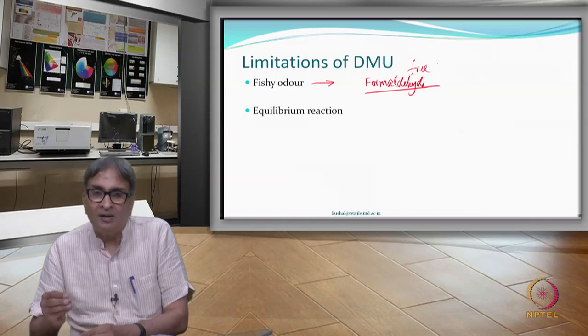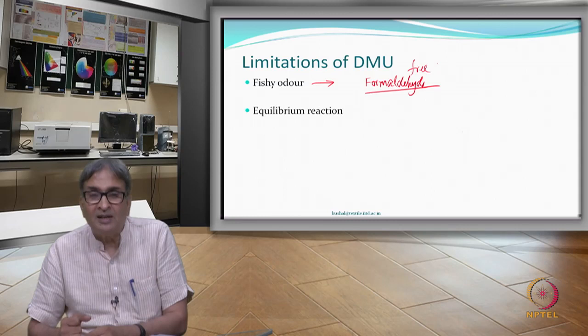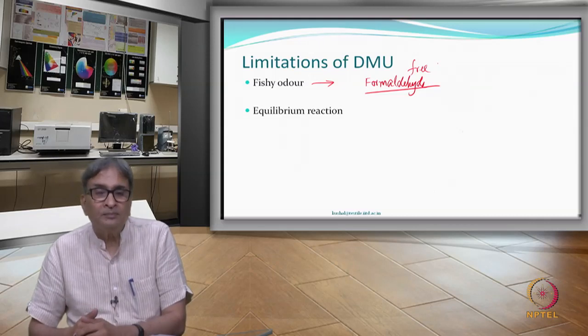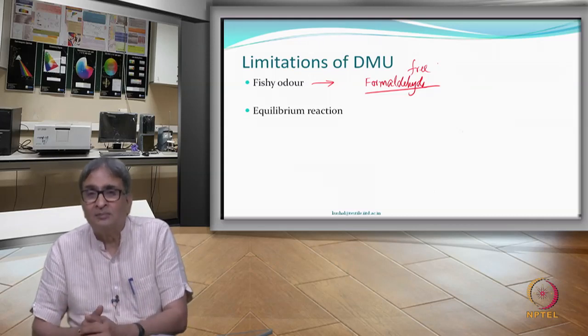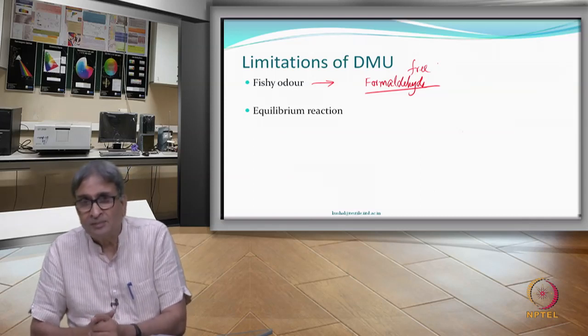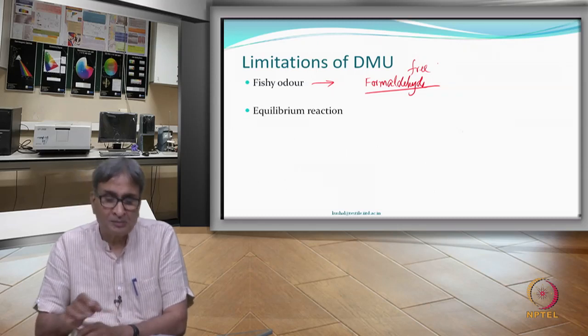It may hydrolyze, maybe very less, but it can hydrolyze, and when it hydrolyzes, a free formaldehyde can be generated in the washed fabrics, in the stored fabrics, in the fabric which have been kept in a moist condition for a long period. So, when you open it, you see smell. So, people did not like it, that is one part, and so one worries about it.